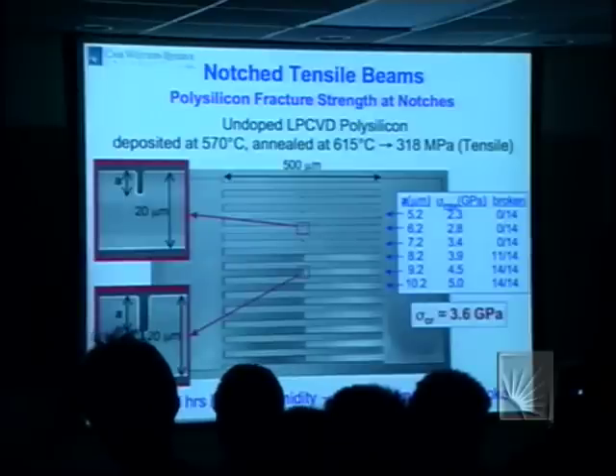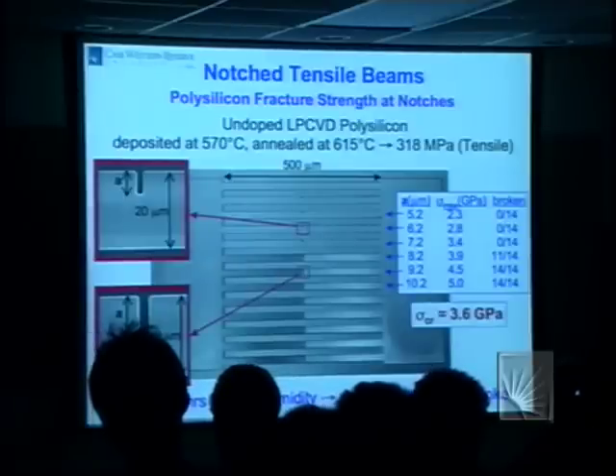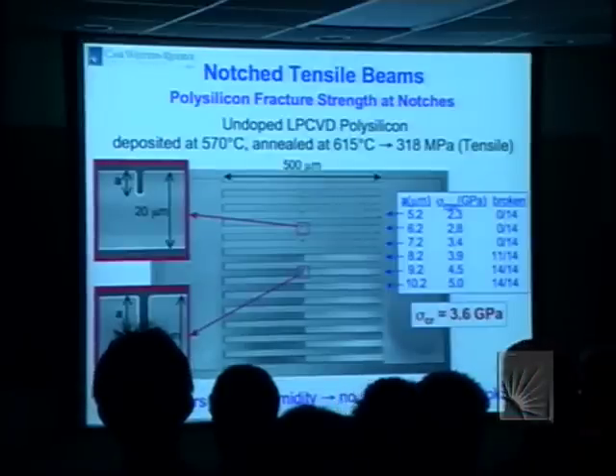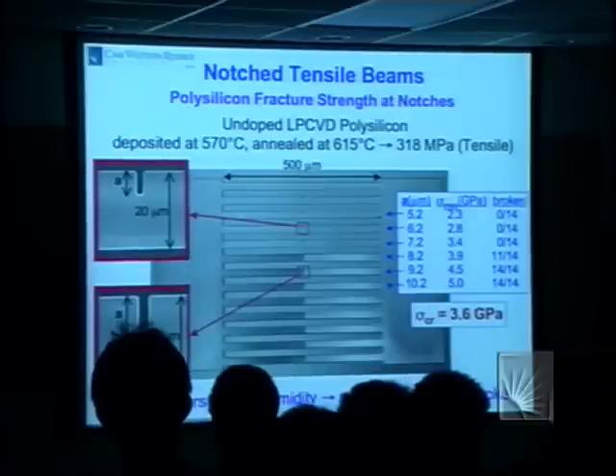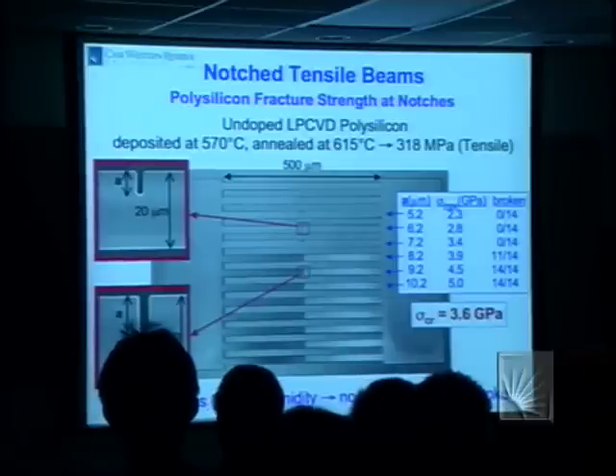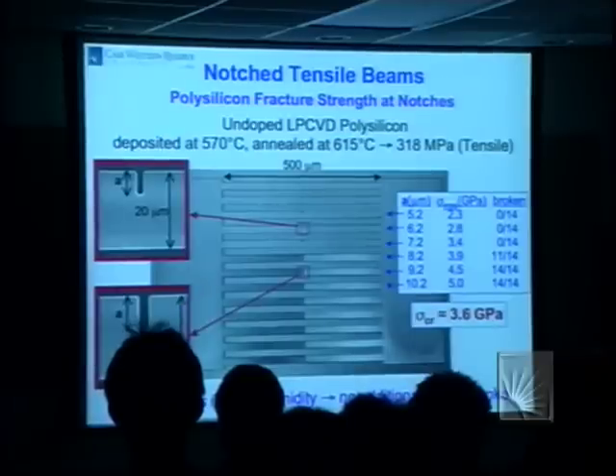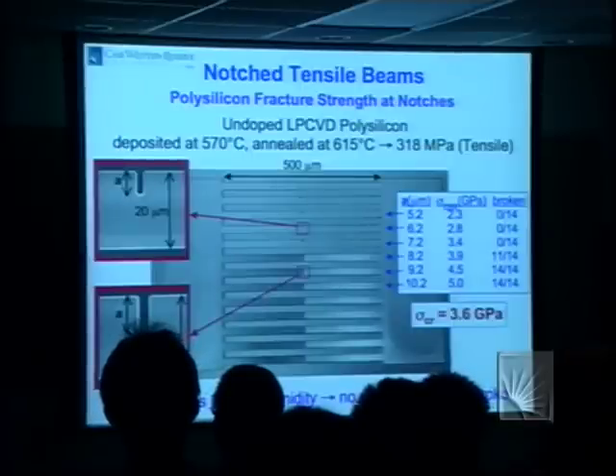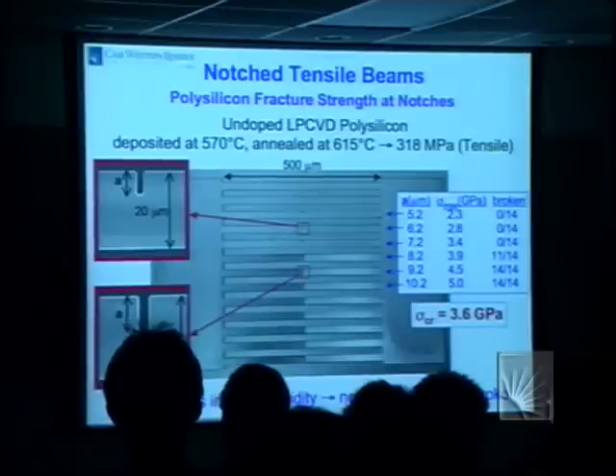The strength, by the way, I should mention, is very sensitive to, it's a brittle material, silicon at room temperature, and like any other good ceramic, its strength depends entirely on the magnitude and severity and the number of defects at the surface, so-called Griffith flaws. And in this case, the defects which cause failure are the polysilicon reacting with the plasma etch. You don't get a perfectly smooth surface, and you can actually calculate what the defects that cause failure are, as I'll show you a bit later.